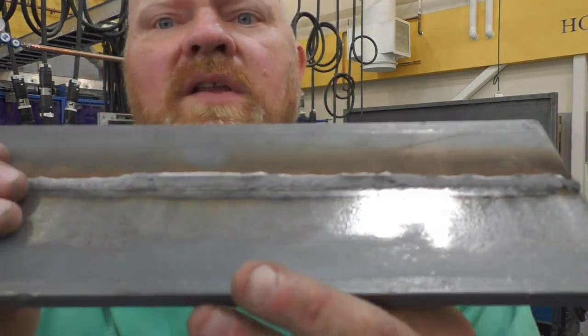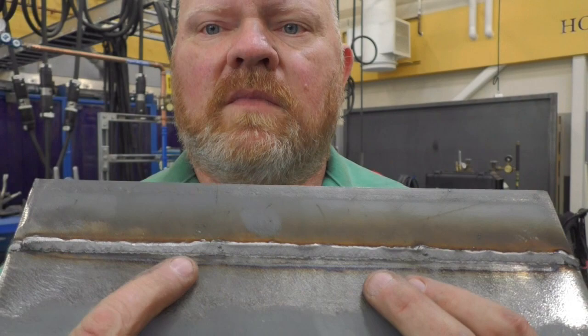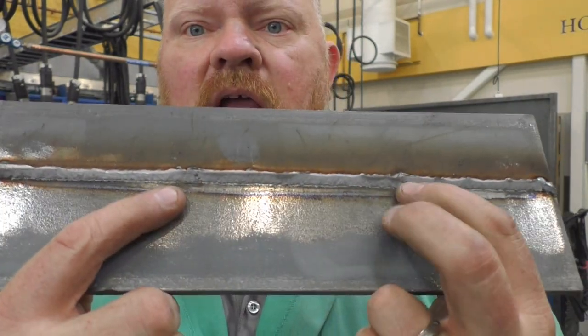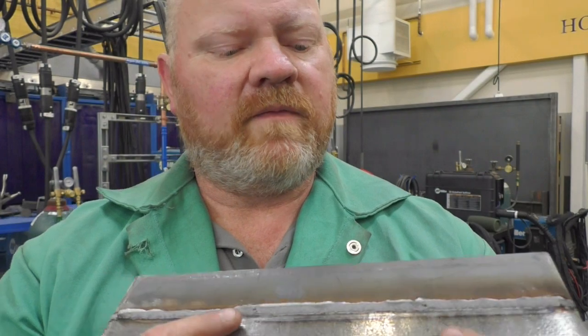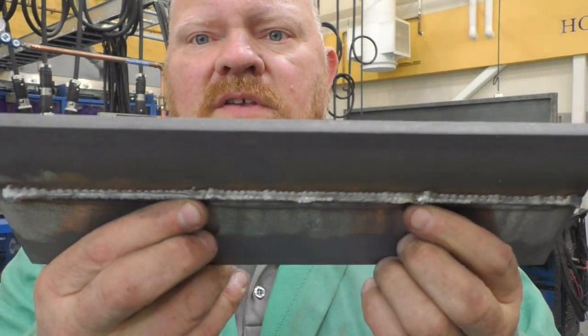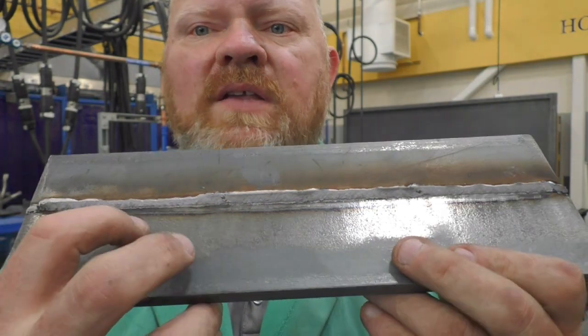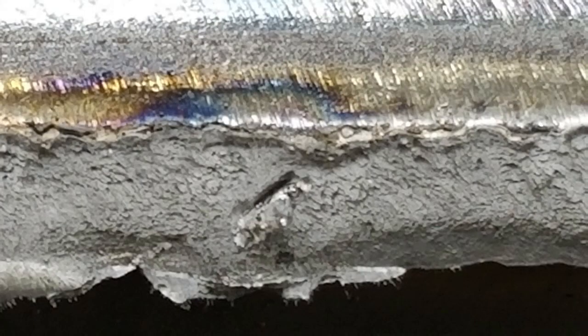Now, the next plate that I welded actually with short arc, and I ran 21 volts and I think 500 inches per minute of wire feed with .023 diameter wire. And I produced a weld that kind of surprised me. Now I don't normally look at the T part of the plate, but I do want to demonstrate here. You'll either be looking at this on video or a photograph. If I roll my fingers around, you can see where the two restarts were, one here and one here. The weld itself is pretty solid looking, but you can see that the restarts were cold.